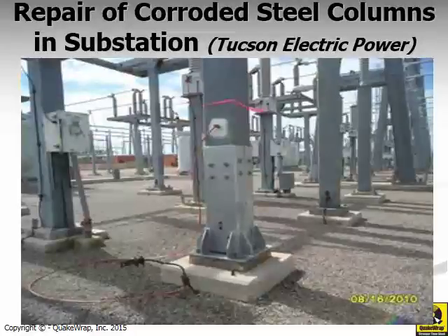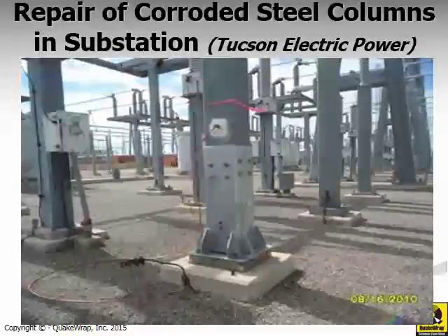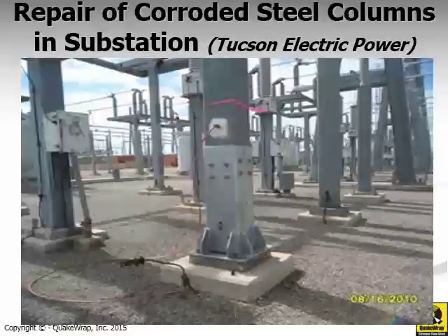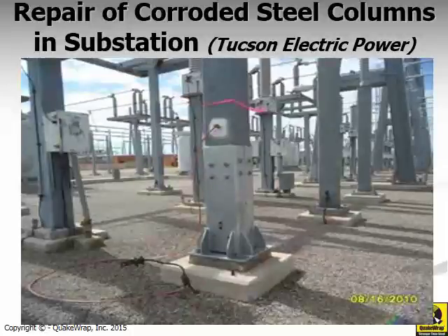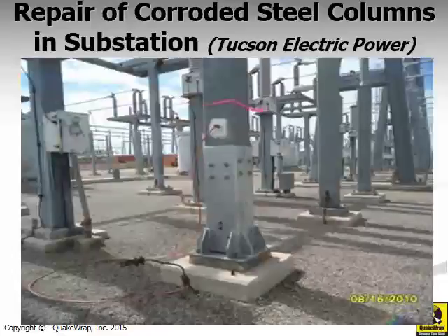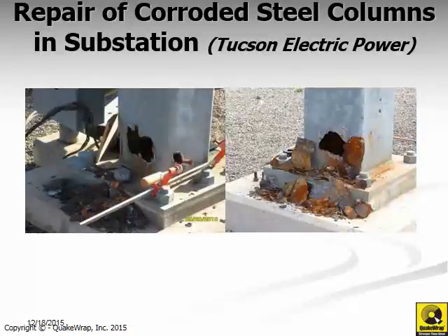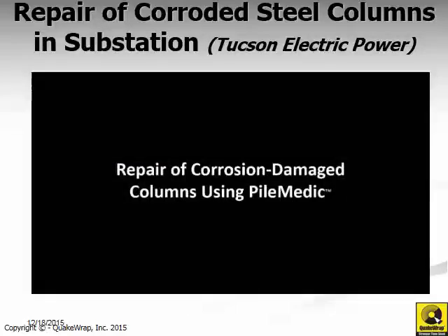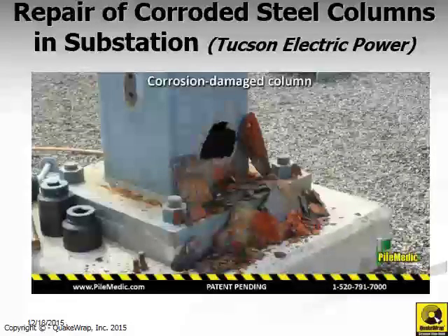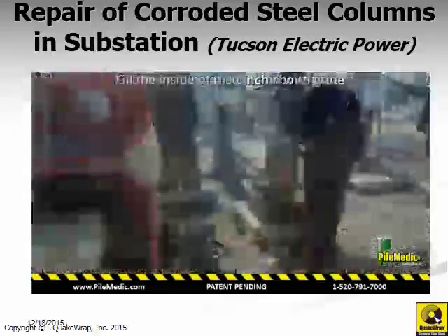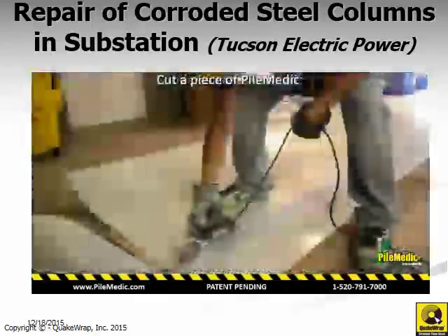So these types of repairs are applicable not only to bridges but also to other industries. In this case, for example, we have been repairing some steel columns for a substation, a Tucson Electric Power substation. Even though these columns were galvanized, they were suffering from a lot of damage and corrosion. As you can see in this slide, when you remove the boots at the bottom of the columns, severe corrosion was taking place. So our repair system is shown in this video, where we make a cut about 3 feet up and fill the inside of the column with grout.